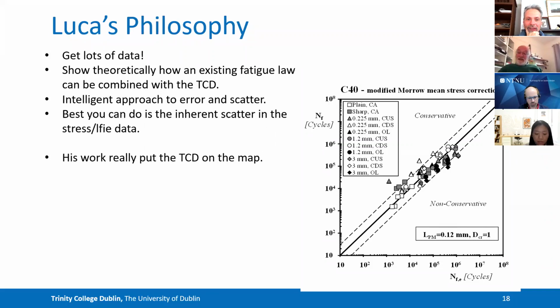And so he plotted these kind of graphs where you plot the predicted number of cycles to failure on one graph and the experimental number of cycles to failure on the other, and hopefully they lie in a straight line. But there is also always going to be scatter, but you don't have to worry about that if that's within a scatter band, which is similar to the scatter band of your original data that you're coming from. And so again, we have a nice criterion of success. And it's very difficult to argue with a graph that has as many data points on it, and they're all doing very well. And I think that's really important.